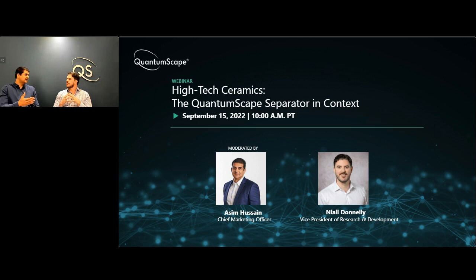Right, and maybe we could touch on this just to remind folks, those are the properties that then eliminate the essential materials that are there in conventional anodes, right? And allow the lithium, could you talk just a bit about allowing the lithium to actually form a solid metallic layer instead of conventional batteries? Sure. So our battery is based on lithium metal anodes. A conventional lithium ion battery uses graphite as the host medium on the anode for lithium. So the lithium ions move through the liquid, through the separator, they reach graphite particles on the anode, and they diffuse and insert into the graphite lattice. In our case, graphite is completely absent. We use lithium metal.